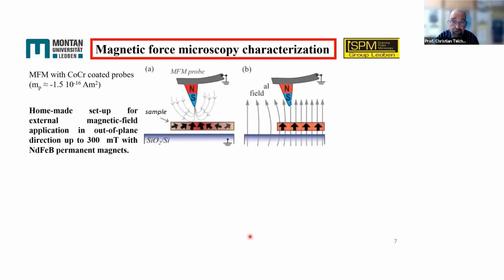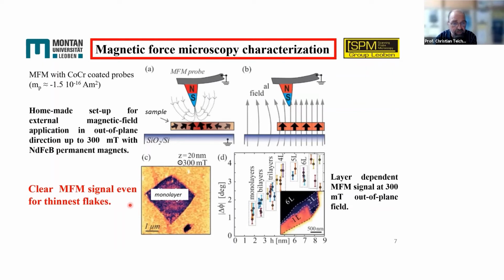Now we use magnetic force microscopy. We are using cobalt chromium coated probes, and we use either these probes without an external field or an external magnetic field applied in out-of-plane direction, where by using neodymium iron boron permanent magnets we could add about 300 millitesla external field. And there is a clear magnetic force microscopy signal even for the thinnest flakes. And we see a layer-dependent MFM signal at 300 millitesla for out of plane. So you see already the monolayer shows a weak but clear magnetic response, and that increases up to 4 layers, and then it stays more or less constant.